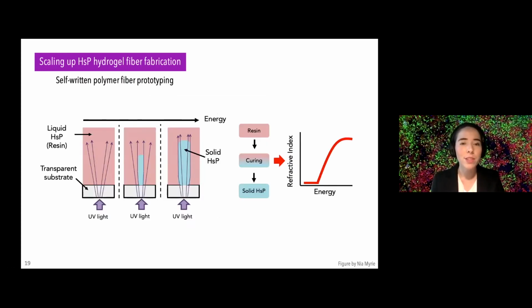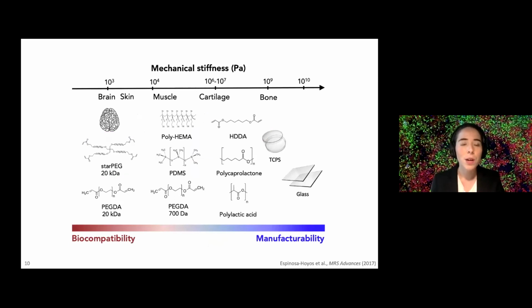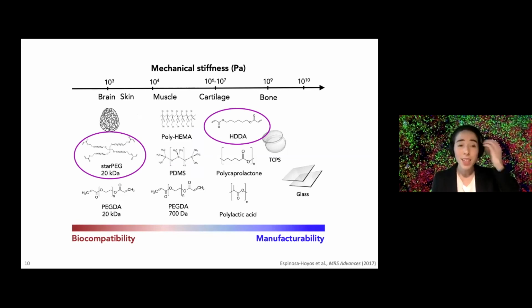And because we have these two very different monomers, this hydrophobic short linker, which is in a stoichiometric excess, so this HDDA, and then we have this very large hydrophilic monomer, I think we probably have hydrophobic domains, hydrophilic domains, and all sorts of defects that help impart this biocompatibility, as well as mechanical properties and this optical behavior that we see.